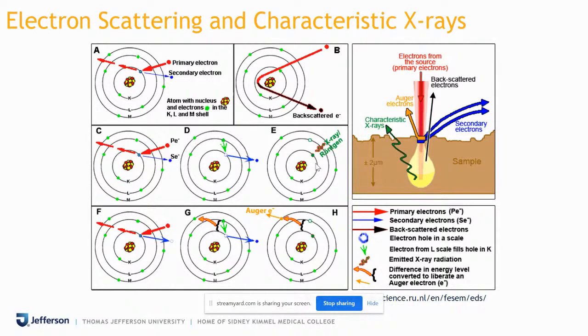Please understand that these X-rays are the characteristic X-rays of the material, and they come out from a depth of approximately 2 micrometer, which is shown on the right hand side in the schematic. So the characteristic X-ray is a characteristic of a material. When we are doing transmission electron microscopy or scanning electron microscopy, the characteristic X-rays invariably come out. And if you have a detector attached to this scanning electron microscope, you can detect these signals and verify what elements are in the material you're looking at, whether it has Fe, carbon, nitrogen, or other elements.